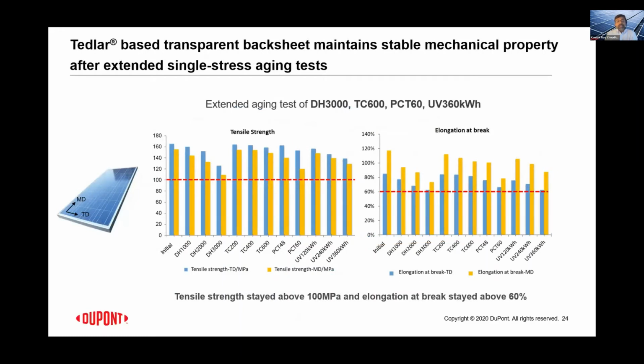This chart is again showing more mechanical properties. As you can imagine, mechanical properties are among the most important properties that we look at. Over here, we are looking at elongation at break, as well as tensile strength, another measure of the mechanical property of the backsheet, under a variety of different tests. So in this case, damp heat 3000, thermal cycling of 600, pressure cooker test of 60 hours, and 360 kilowatt hours of UV. Under all these conditions, what we see here is that the mechanical properties of the backsheets are holding up well above this required internal requirement. This is an internal requirement that we put, which is shown here with this red dotted line. So it's holding up even after these significant hours of these accelerated testing regimes.